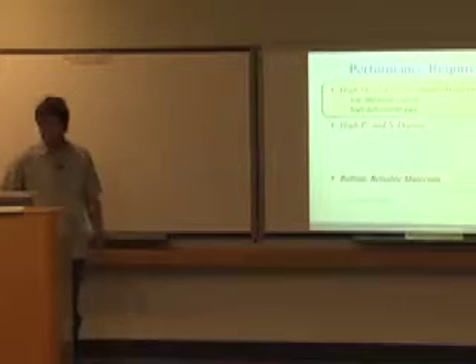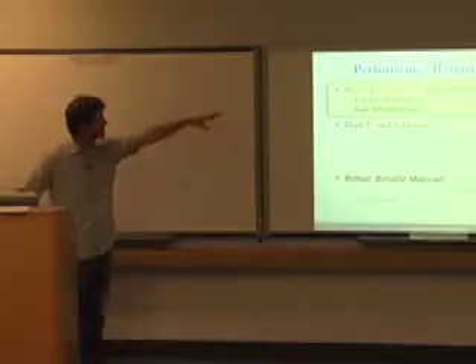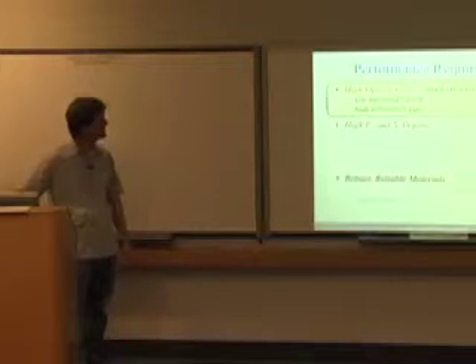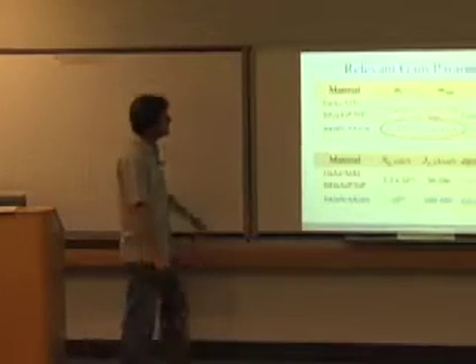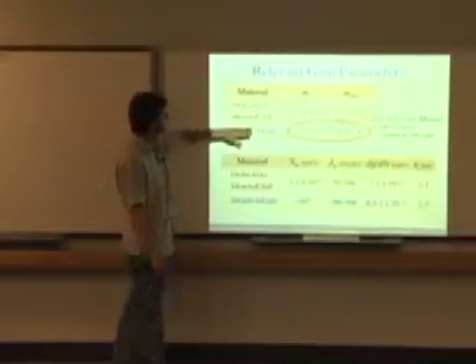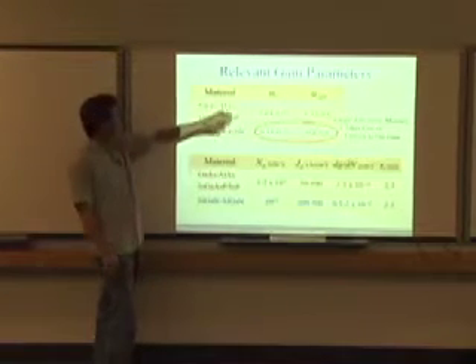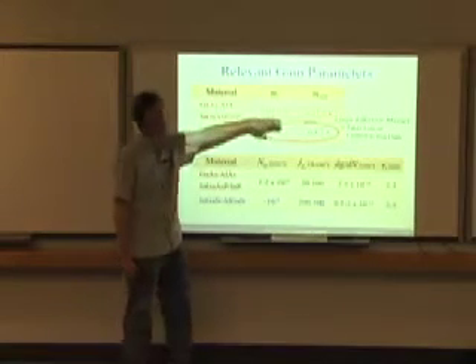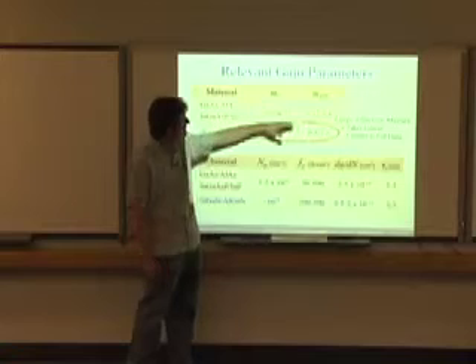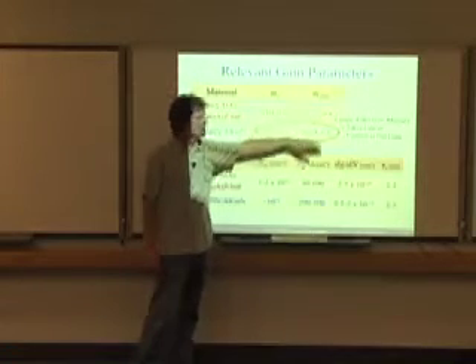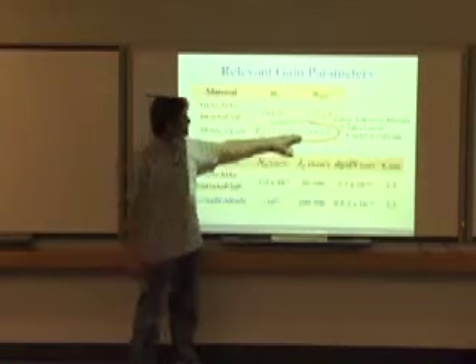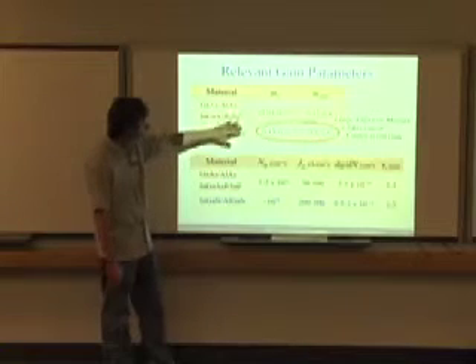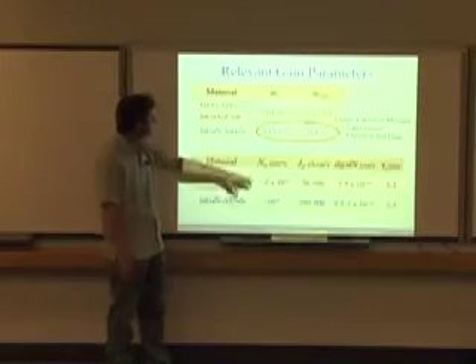So moving on from cavity requirements, there's also performance requirements. It requires high optical gain and small effective masses, which can lead to low threshold currents and high differential gain. If you compare standard materials to InGaN, gallium arsenide and InGaAs really enjoy very small conduction band effective masses. Heavy hole masses were larger. But if you look at InGaN, the situation is quite a bit worse. And what this leads to is much higher transparency carrier densities.